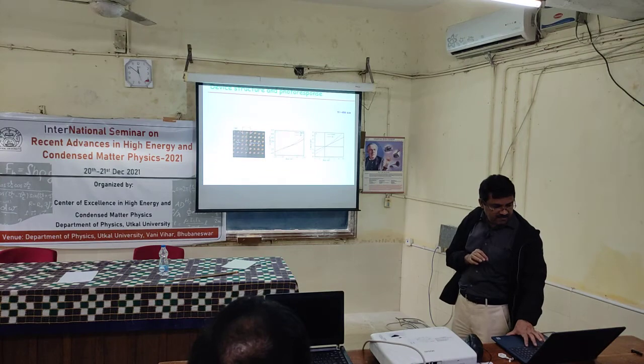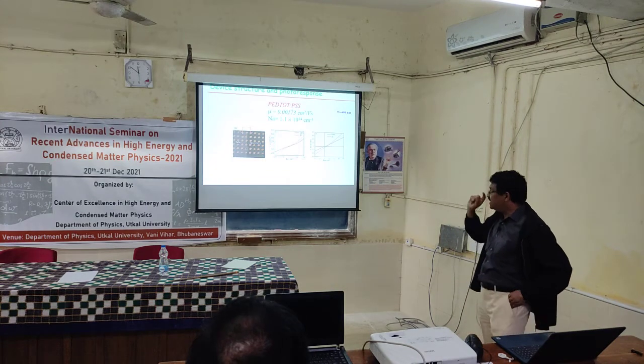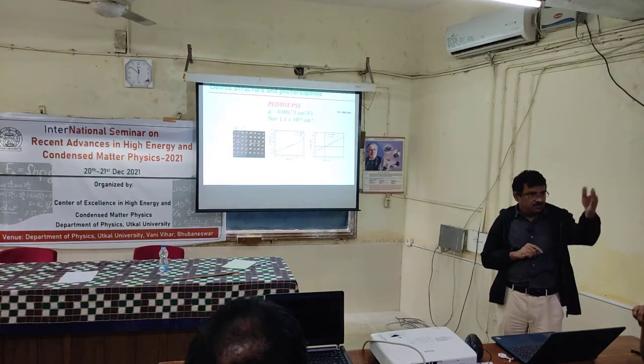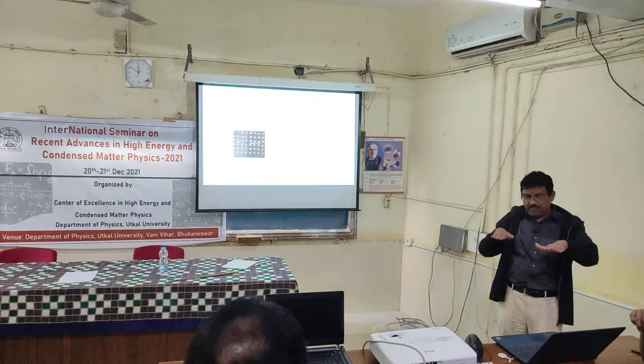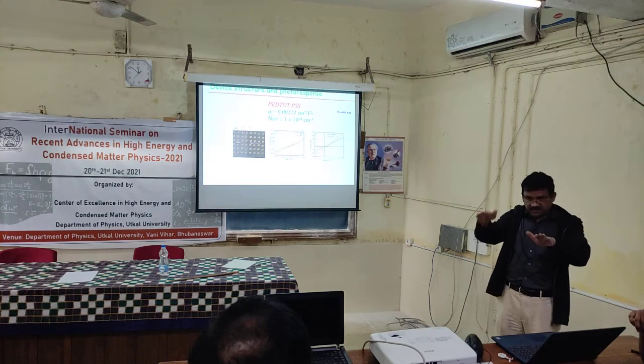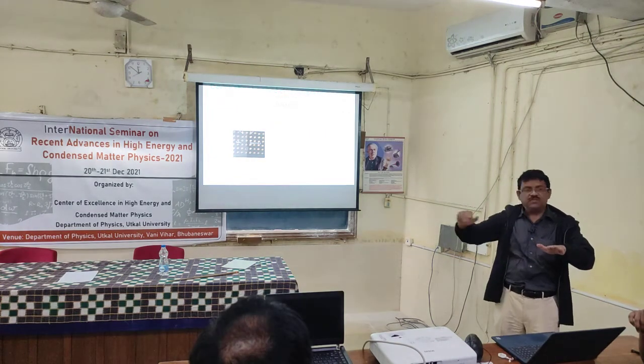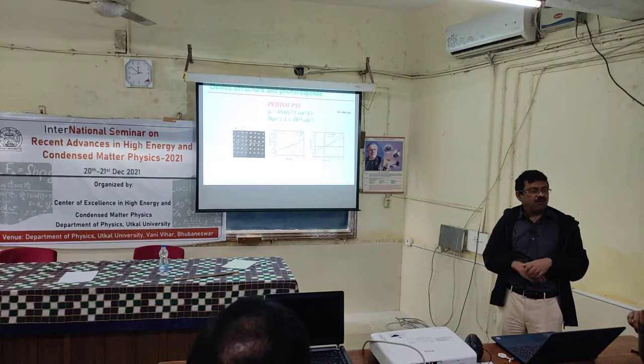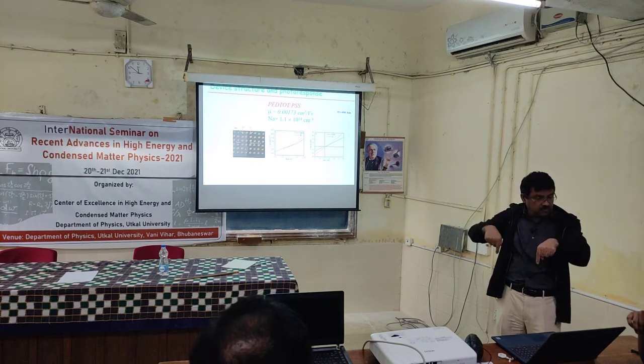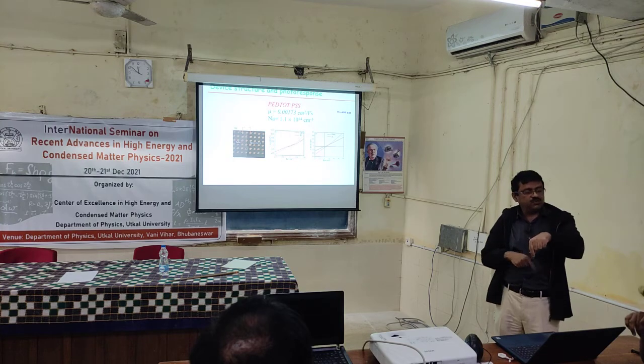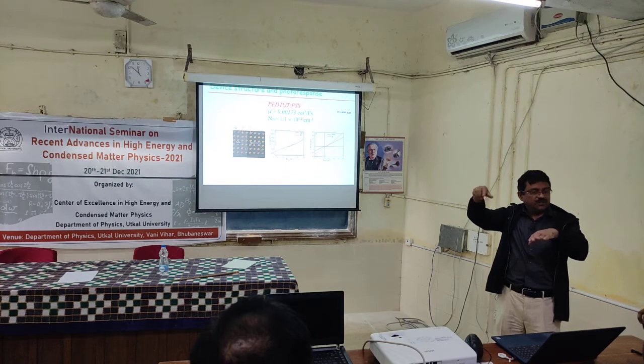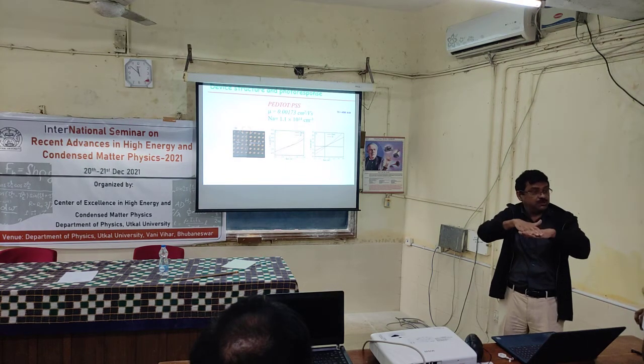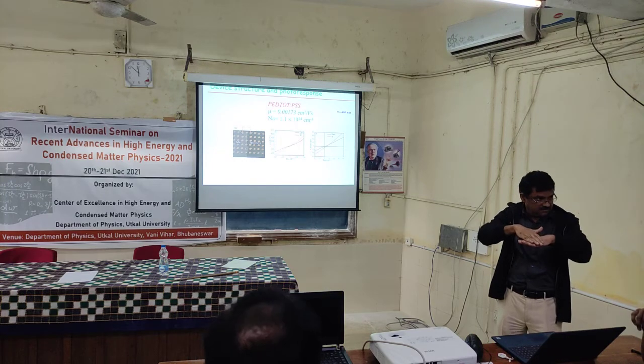So I have to deal with a p-type material. Then we realized that PEDOT:PSS is a p-type polymer. So we took the SnSe2 film, and one part we kept free, and a part of this SnSe2 film we covered with PEDOT:PSS. Now instead of taking two contacts from SnSe2, we have taken one contact from SnSe2 and another contact from PEDOT:PSS. So the PEDOT:PSS and SnSe2 should behave like a PN junction.